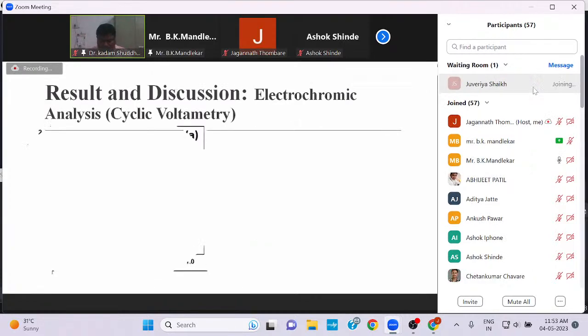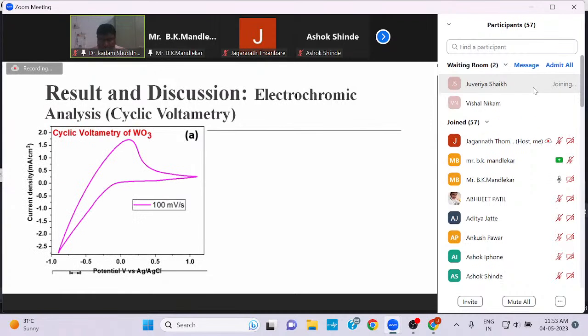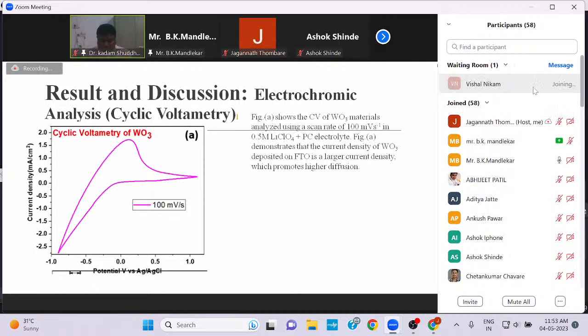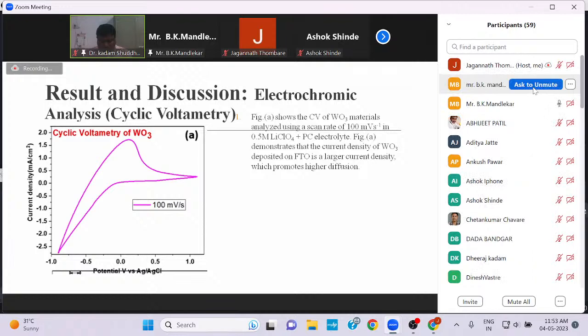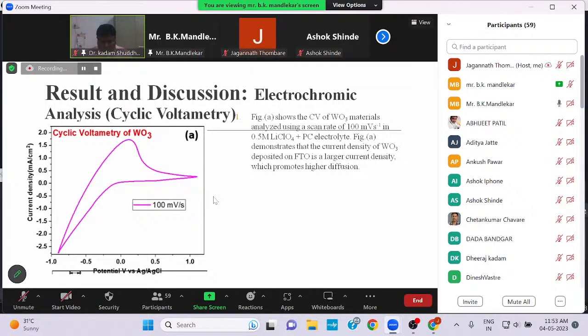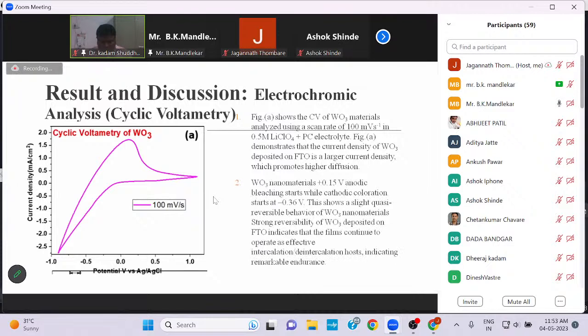Then in electrochemical studies, cyclic voltammetry of WO3, where we found a large area. It shows the CV of WO3 analyzed using a scan rate of 100 millivolts per second in 0.5 molar lithium perchlorate electrolyte. It demonstrates that the current density of WO3 deposited on FTO is large, which promotes higher diffusion. For WO3 nanomaterials, at plus 0.15 volt anodic bleaching starts while cathodic coloration starts at minus 0.36 volt, which shows the reversibility behavior of the nanomaterials. Strong reversibility of the WO3 deposited on FTO indicates that the film continues to operate as an effective intercalation and deintercalation host and indicates remarkable endurance.